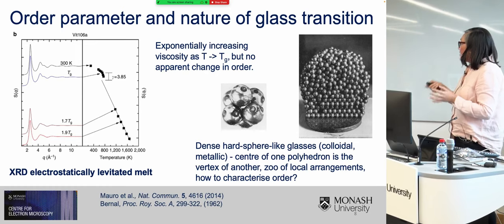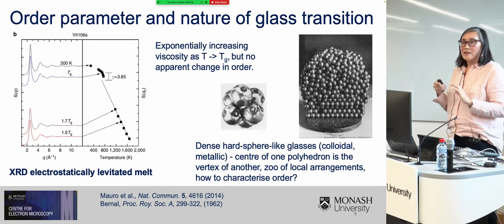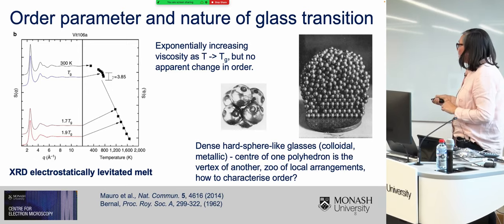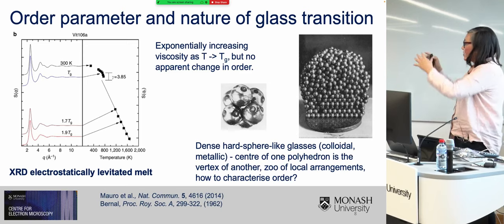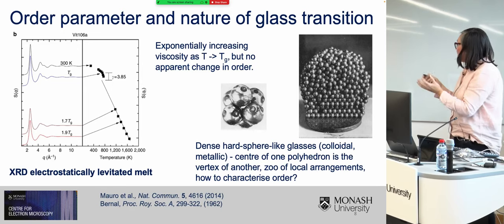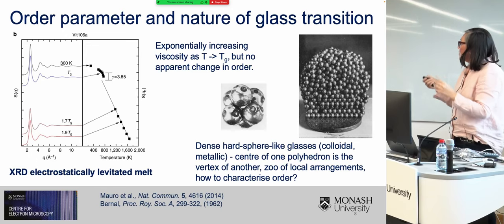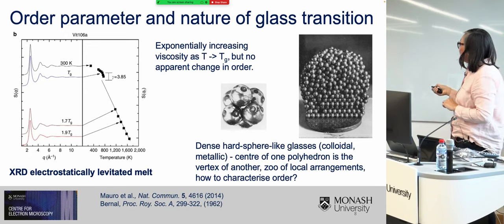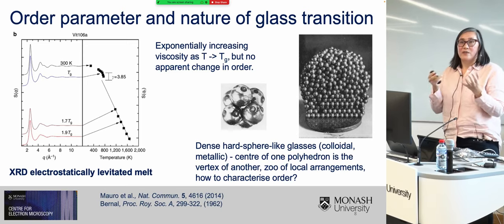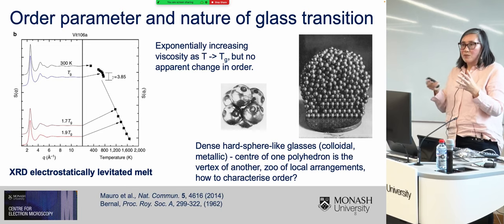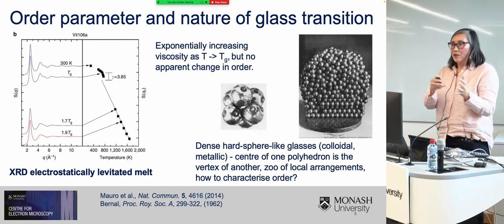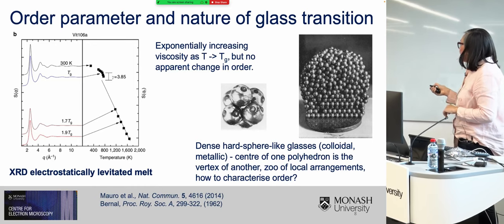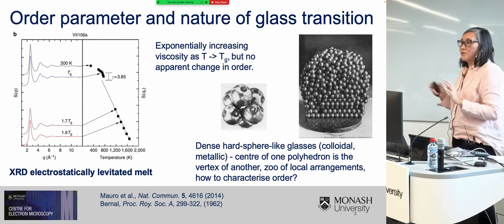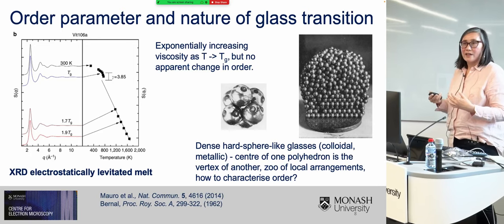Now, the glasses that I'm going to be talking about today are actually quite nice model systems. These are hard sphere glasses that are formed from colloids or metals. And these systems are dense, so they're quite nicely modeled by a dense random packing of ball bearings, as you see here in this picture. And they're dense in the sense that the vertex of one polyhedron is actually the center of the next polyhedron. So there are no gaps or spaces, no areas where you might have stronger order or less order. And these glasses have a veritable zoo of different local arrangements. So how can you characterize that and how can you capture it?